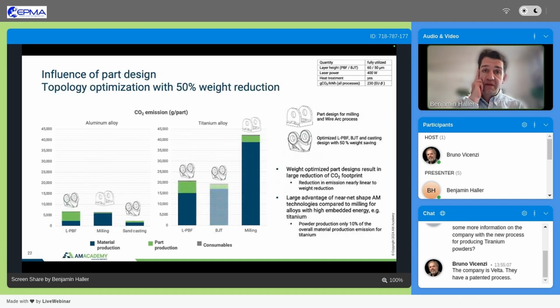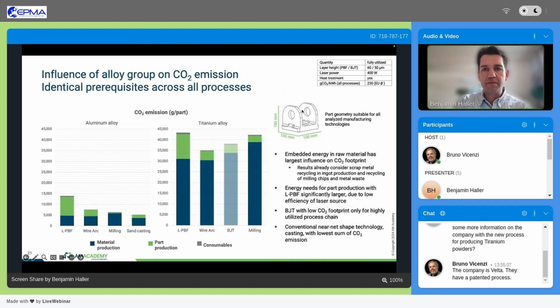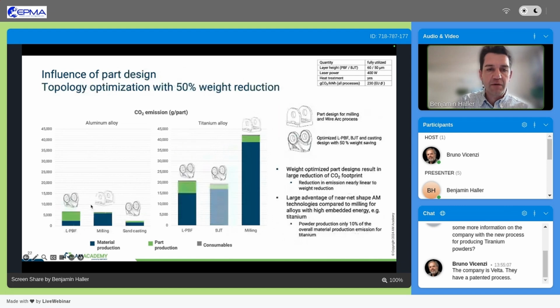Then another topic is the part design itself. So topology optimization: what we look at here, again for aluminum and titanium, is that what you saw was a part that was produced for milling. And this is often not optimal for additive manufacturing, so it might not be a fair comparison. You saw LPBF had roughly twice that of the milling. Now milling has not changed, but for laser powder bed fusion we have only 50% of the volume. And we see already for the aluminum part that we get on par.